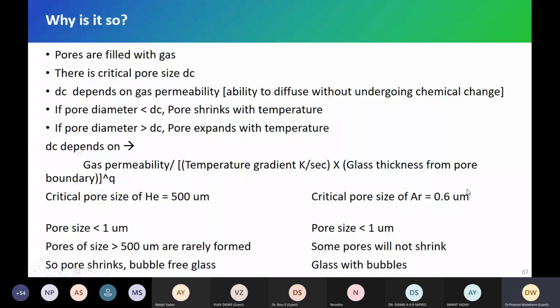If your pore size is, suppose, 1 micron, it is more than this critical size for argon, so it will form a bubble if you are using argon. If you have 1 micron pore size with helium, it is much less than the critical size, so it will not expand; instead, helium will diffuse out. So that's how we manage these bubble things. But even though you are using these optimum conditions, bubbles can still form. There are many reasons. It's not so simple.